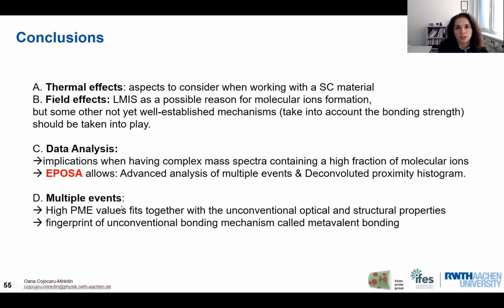And also the multiple events at the end fit very nicely, so this very high probability of multiple events that we have systematically observed for a particular class of materials fits together with the unconventional optical and structural properties and can indeed be considered as a fingerprint for the unconventional bonding mechanism,